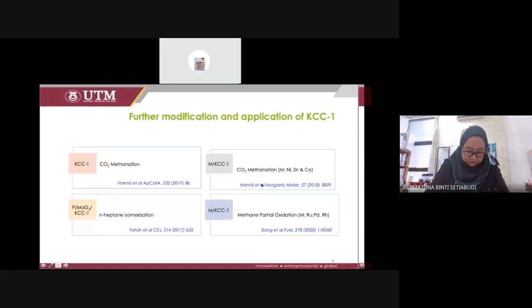Then Hamid also tried the modification with metal loaded on the KCC1. The metals used in this study are nickel, zinc, and cobalt. We found that when we load different metals on the KCC1, a different mechanism of the CO2 methanation was found. Okay, the nickel and cobalt followed the dissociative mechanism, while the zinc underwent the associative mechanism to convert the CO2 to methane. Okay, and then the good one, of course, the evergreen metal, is nickel.